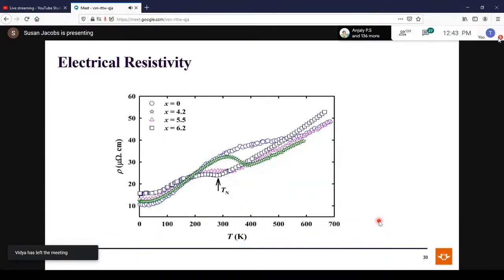And then electrical resistivity, as expected, as you increase the vanadium concentration, again, you suppress the transition. You can see for 4.2, it is there. For 5.5, and then 6.2, it's the lowest. So TN is suppressed as expected.